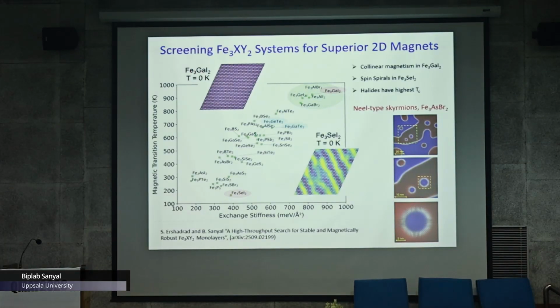One is iron 3 gallium I2. Here you see a collinear magnetism, very high Curie temperature. But on the contrary, this iron 3 selenium I2, at T equal to 0 Kelvin, shows a spin spiral structure. So you can see a variety of magnetic structures in this study. And if you look into the iron 3 arsenic bromine 2, you see some Neel type of skyrmions. They also appear. Now, the whole idea of studying this is to motivate experimentalists whether it is at all possible to synthesize these materials, which is the first step.